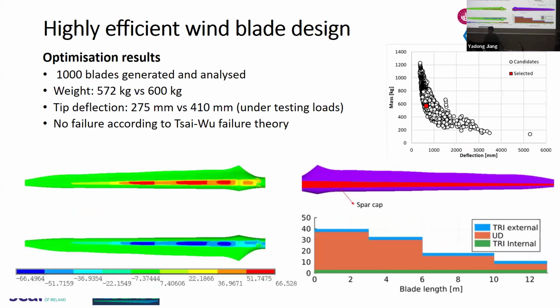So here is an analyzed result. We generated 1,000 different blade internal designs, and we analyzed these 1,000 blades under the same load case. Here is a plot showing the mass and the deflection of the blades, and each dot represents the performance of a single blade design. From that, we selected one blade which is close to the lower bound of this scatter, and this one has a balance of weight and deflection. The weight will be a little bit smaller than the reference blade, and the tip deflection will be much smaller than the previous one, indicating a good increase in stiffness.